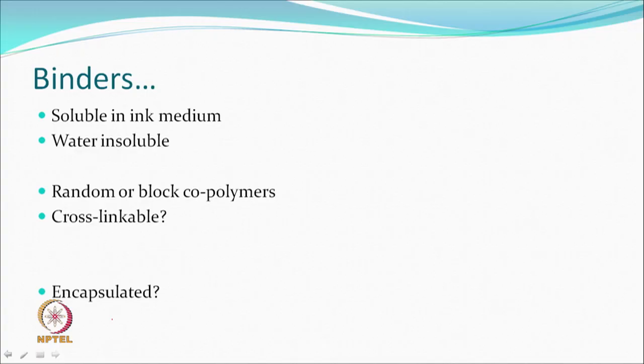Sometimes to avoid these gelling issues, because they are not water soluble or they are less water soluble, but they definitely are hydrophilic compounds to begin with, they may be encapsulated and they get exposed when they are outside. So, they would not gel inside, they would not clog the material, and once they are cross linked, they will become less water soluble, because if the cross linking takes place before it is ejected, then it is a hopeless situation.